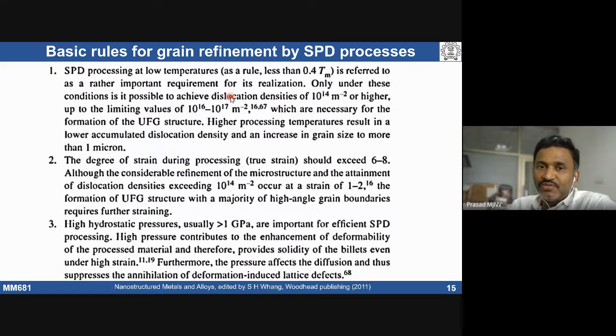These are taken directly from this textbook. These are 5 important rules in order to refine the grain size without much shape change in the material. The first one, we need to have a low temperature. Only then can we induce very high dislocation density. If the temperature is high, it undergoes easy recovery, and it's not easy to refine the grain size. There we talk about DRX, DRV is going to take place.